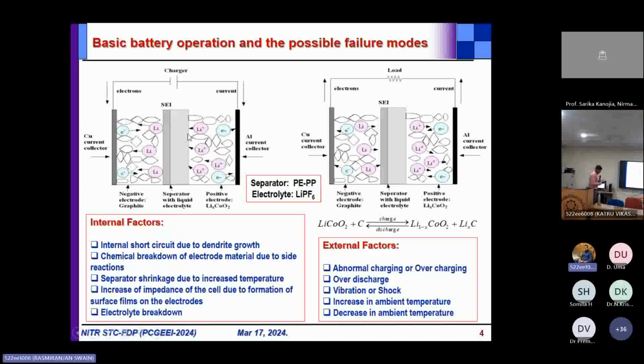This contributes to almost 90% of the battery degradation. There are also other degradation mechanisms in a lithium-ion battery, and some degradation happens at low temperatures. That kind of degradation is called the plating mechanism. But here we are talking about the SEI, which contributes to the major part of the degradation. Because of the formation of the SEI layer on the anode surface, it offers a restriction to the passage of lithium ions when they move from the cathode to the anode. The lithium ions will face obstruction from the SEI layer. Every battery has some internal resistance within it, and because of the deposition of the SEI layer on the anode surface, there will be an extra resistance due to the SEI layer. I will show you that at a later part of the presentation.